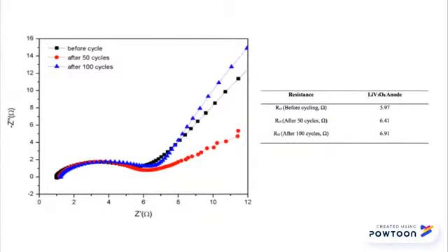The impedance of a lithium-ion battery is mainly attributed to anode impedance, especially charge transfer resistance. It is clear from the table that the charge transfer resistance increased from 5.97 ohm to 6.91 ohm. A slow increase in charge transfer resistance during the cycling process indicates that the battery anode maintains its performance. That means the anode degrades slowly in the process.